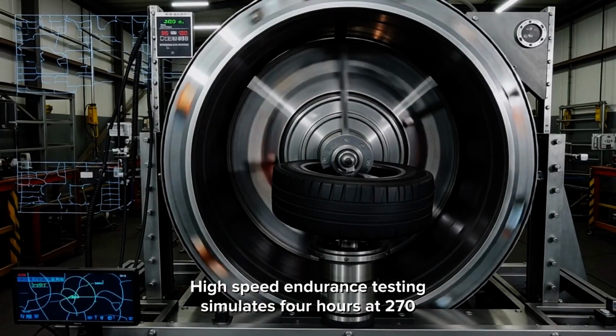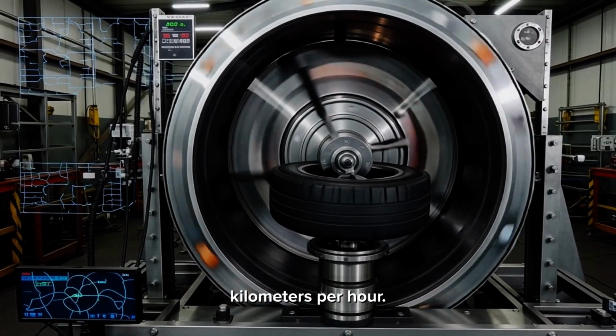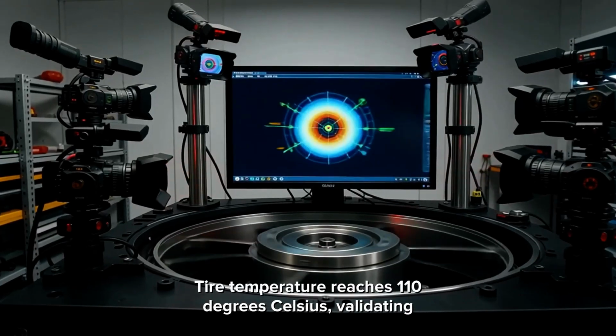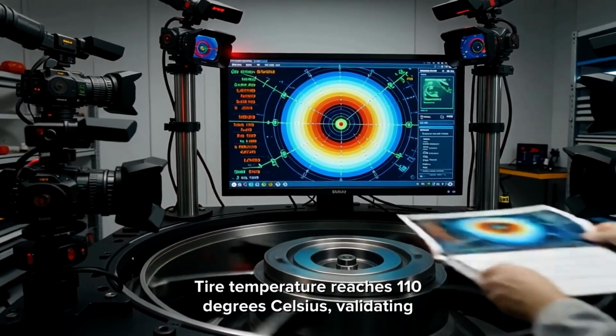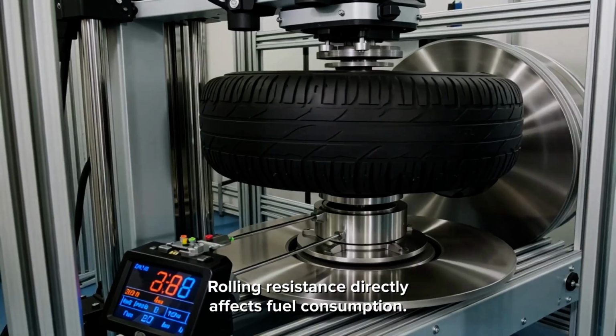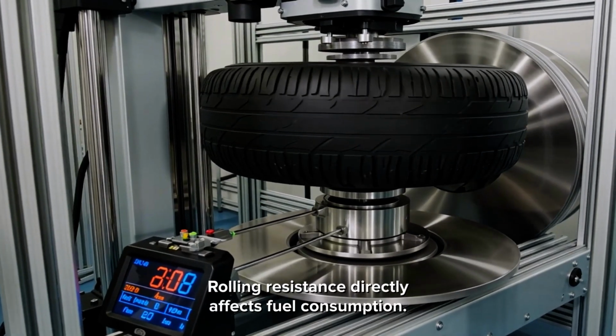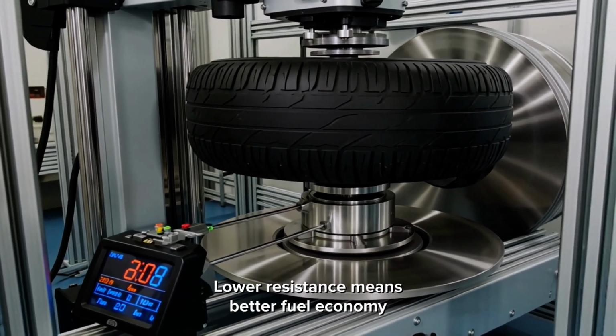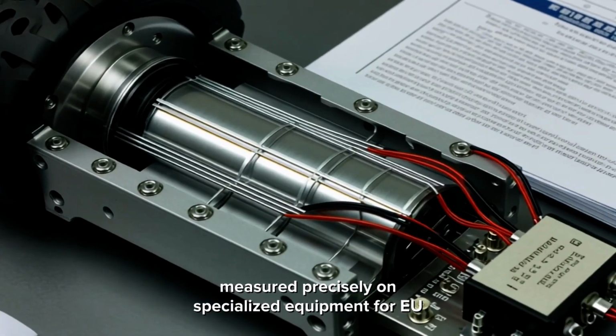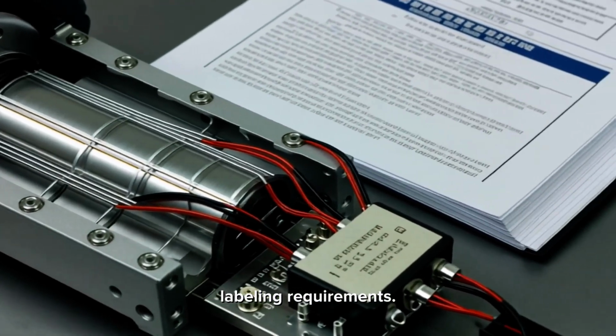High-speed endurance testing simulates 4 hours at 270 kilometers per hour. Tire temperature reaches 110 degrees Celsius, validating the speed rating. Rolling resistance directly affects fuel consumption. Lower resistance means better fuel economy, measured precisely on specialized equipment for EU labeling requirements.